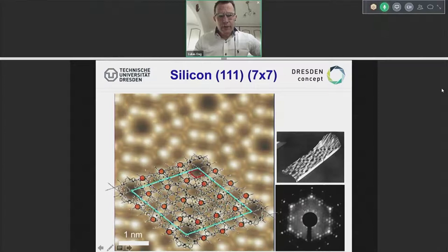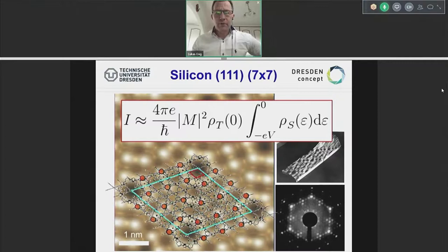And even these 7 by 7 are not equal. So if you go and really solve this equation that we had before for this system, you will see that the rho s, the sample density function, is quite different. Hence, the chemistry on the right half and on the left half will be completely different. That's exactly what this contrast looks like. One of the very prominent examples was really that STM was able to solve this.